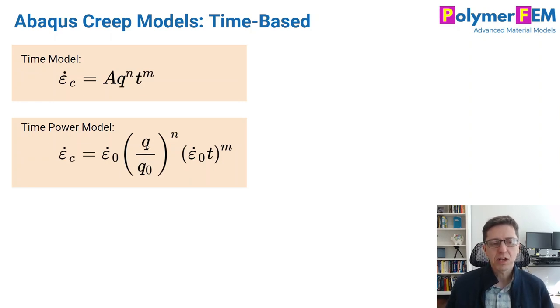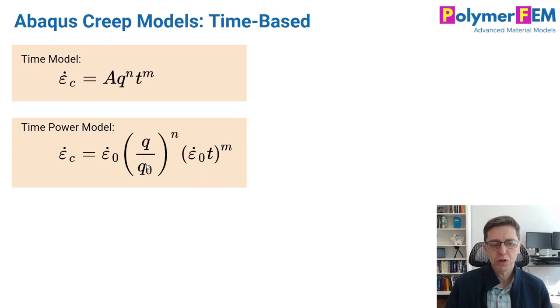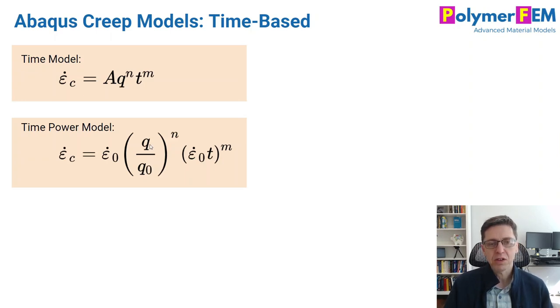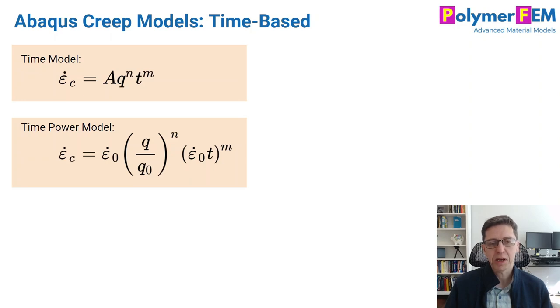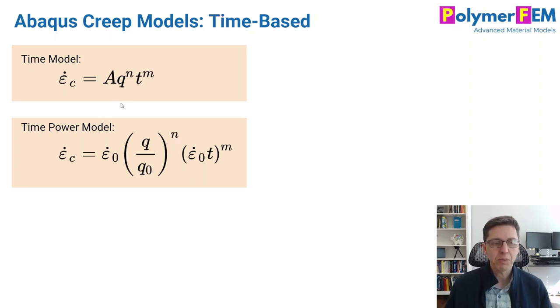The newer version of it is the same, so functionally they're identical, but there is a big difference here. In the second one, you take Q, the stress, and divide it by a parameter called Q0. And this is hugely better because what if Q, the stress, is in SI units, say 1×10^6, 1 megapascal that is, raised to a power of 5 or something, so 1×10^6 to the 5th power becomes a very large number.